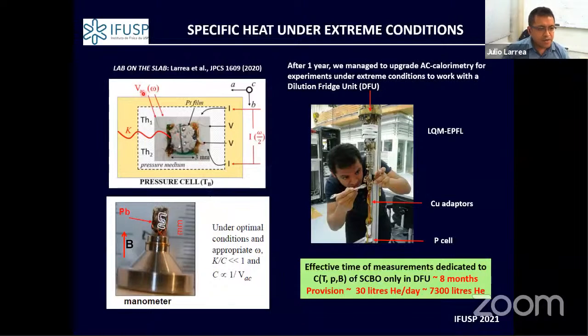On the other side, we try to measure the modulating temperature that would be related to the specific heat, simply by a signal in a double harmonic with lock-in. Of course, the thermal link that your sample has with the surrounding, considering that the sample is also immersed in a pressure medium and in the pressure cell, is important, because according to how stable your temperature is, you also end up with a different influence on your equation of state.